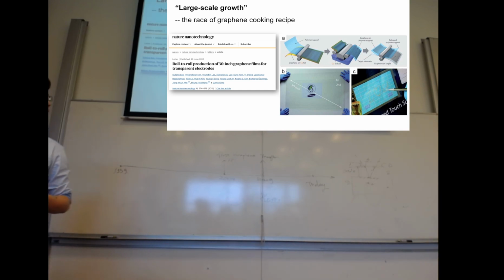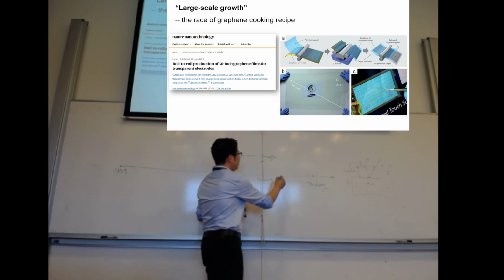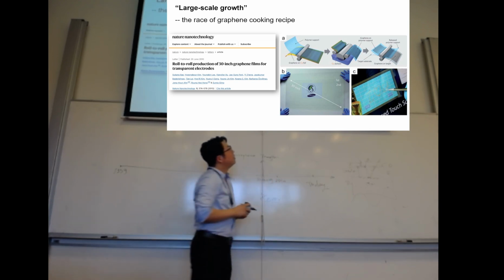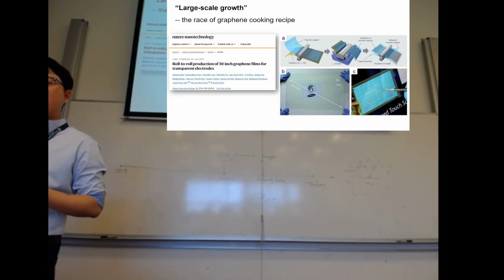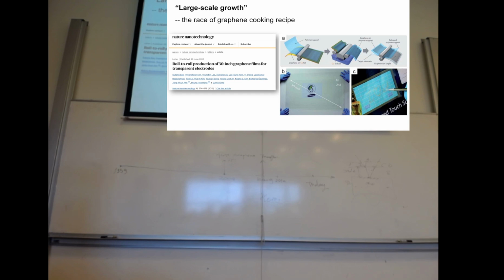So in 2010, which is the year I entered my PhD, Samsung published a very famous paper using this wet transfer technique. They had enough money and enough people to do this experiment. They enlarged this transfer into a roll-to-roll method, and they grew graphene on a larger scale of copper foil, with a very complicated machine. At the end, they could get a 30-inch film of graphene, like this one. They even demonstrated a touch screen using graphene. And that made people really excited for the future of graphene in 2010.